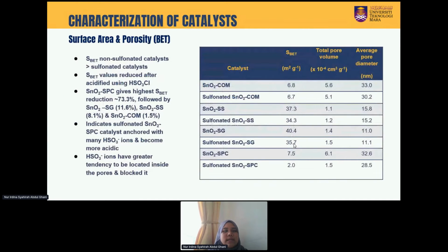Next one is about the BET. As you can see here, the BET of the non-sulfonated catalyst is greater than the sulfonated. From this, we can conclude that SnO2 SPC gives the highest BET reduction, about 73.3%, followed by sol gel and also solid state.